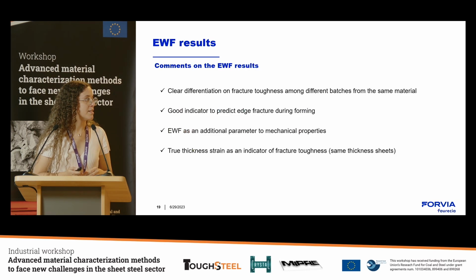Finally, with just some brief conclusions that Valerie already said, we can see a clear differentiation in fracture toughness between these three materials from different batches, but the same mechanical properties. It can be a good indicator to predict edge fracture during forming, and also it can be an additional parameter included in the typical mechanical properties used, and true thickness strain presents a good correlation with fracture toughness.